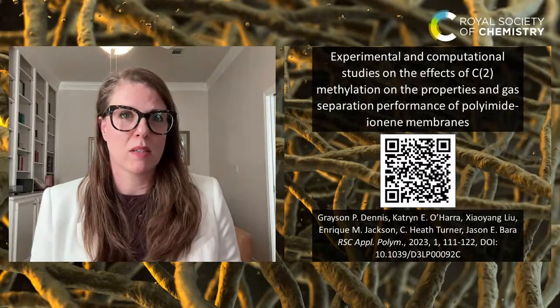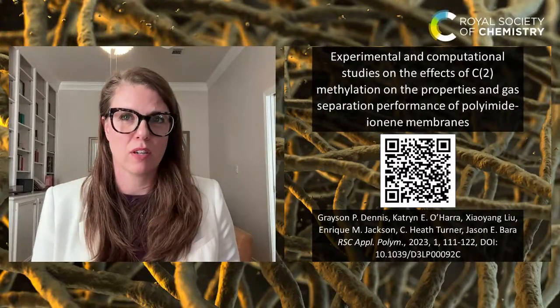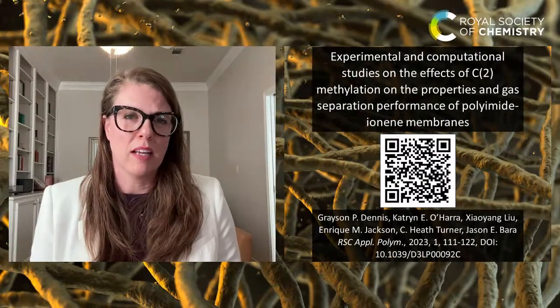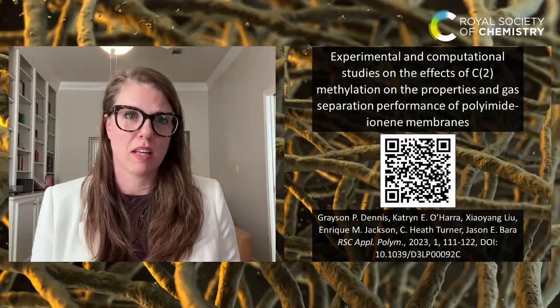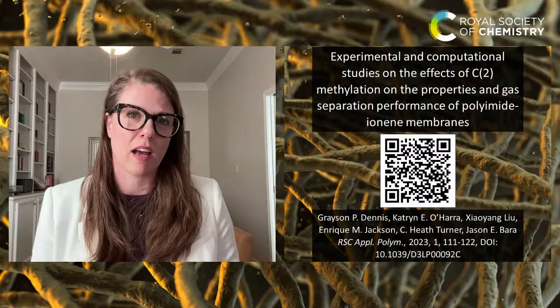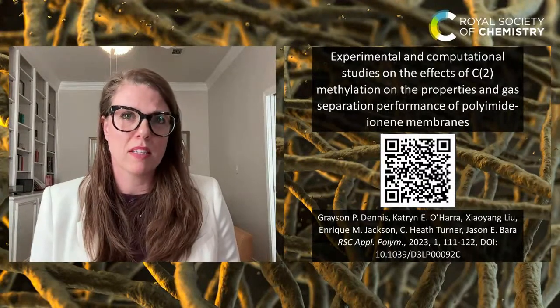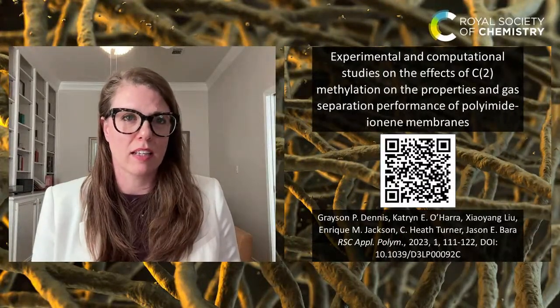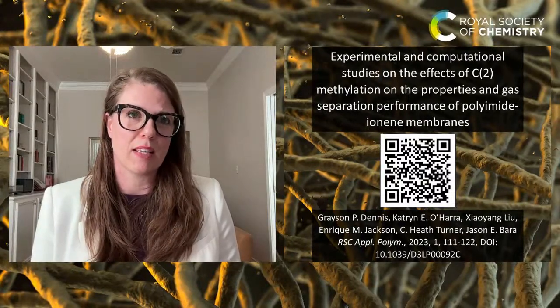They first applied quantum mechanical calculations and molecular dynamics simulations on the monomers and found that methylation decreases intermolecular interactions between the cation and counterion. Experimentally, they cast the polymer into ionic liquid-containing membranes and characterized the thermal properties and morphologies, as well as gas